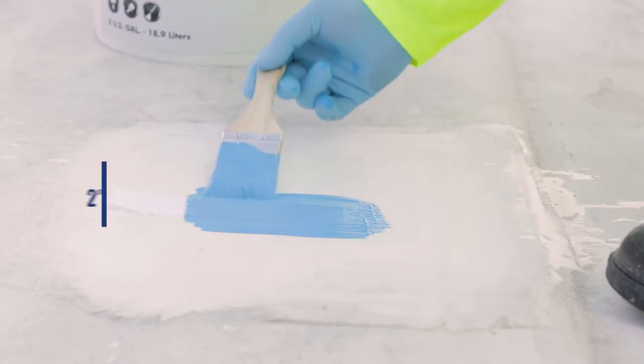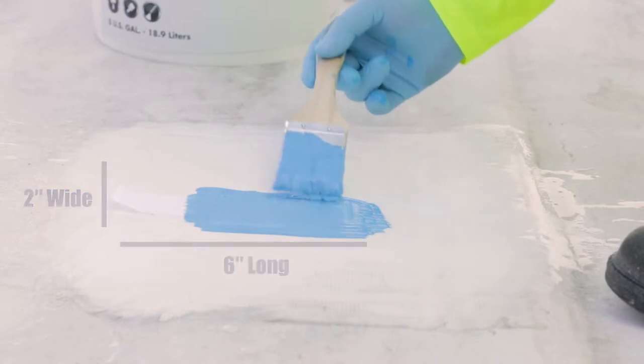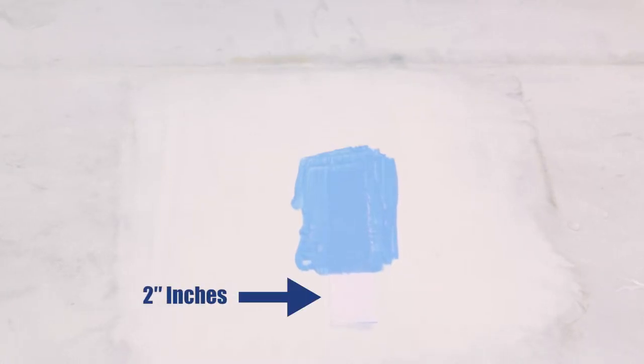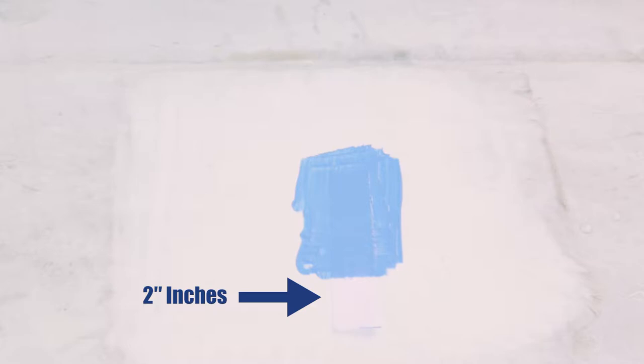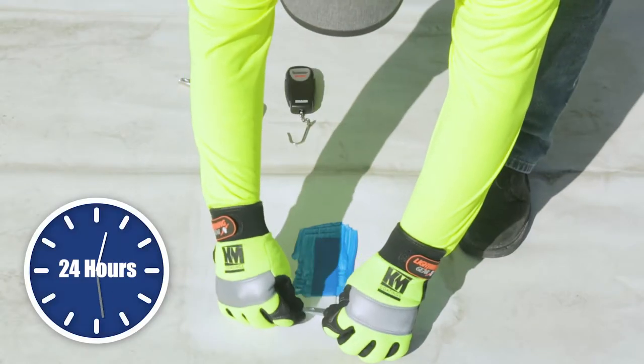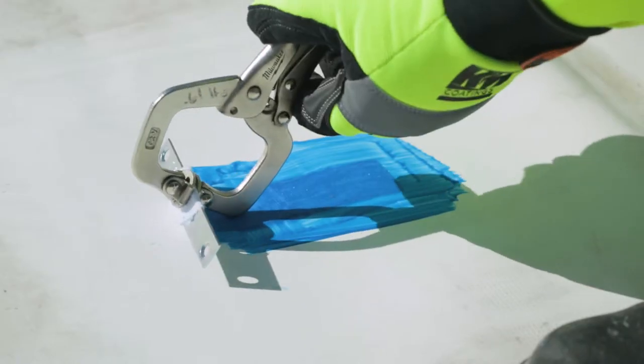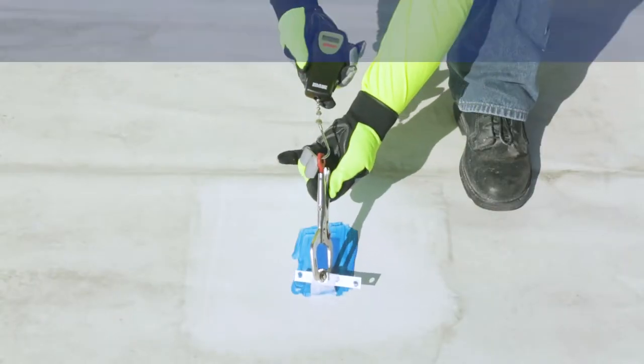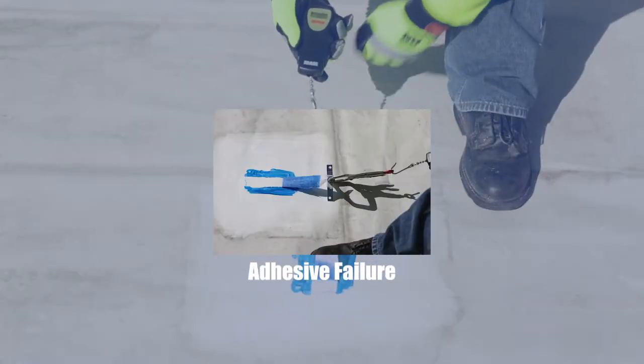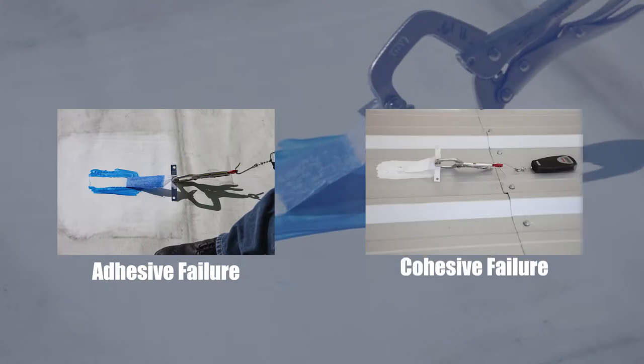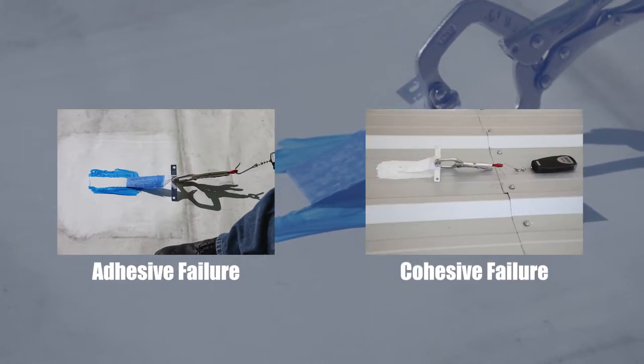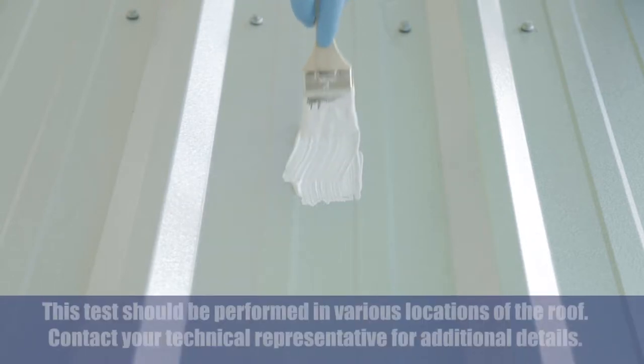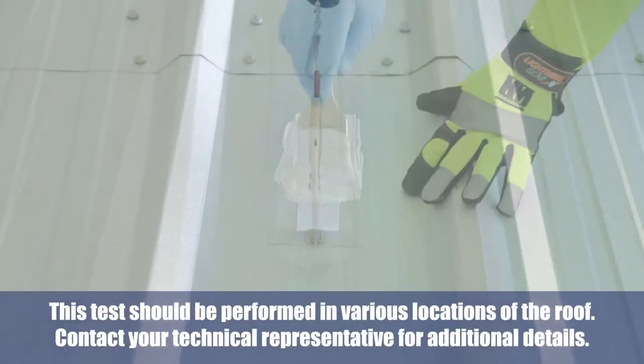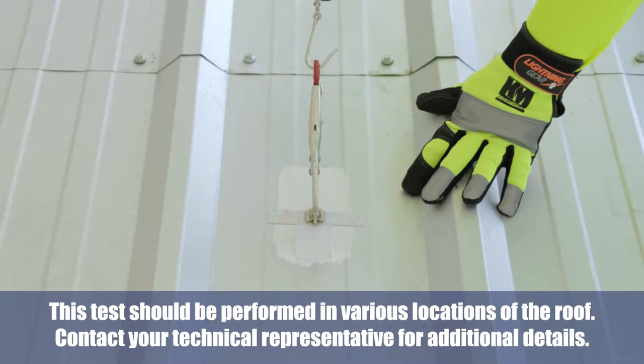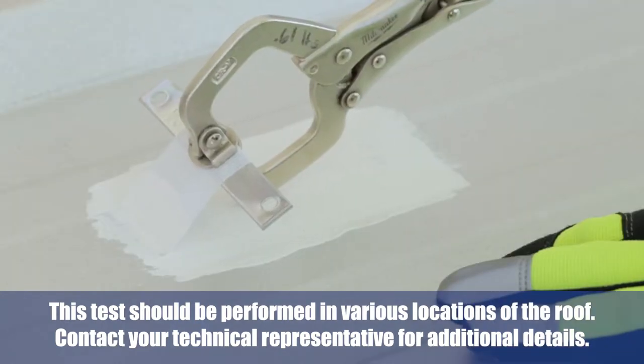The strip of mesh should be approximately 2 inches wide and 6 inches long. When applying the mesh, make sure to leave 2 inches uncoated to pull after product application and cure. We recommend a minimum dry time of 24 hours before the polyester strip is pulled. If the coating comes off the substrate clean, adhesive failure occurred and a primer may be required. If coating is left on the surface, it is possible the primer may not be required. The same test can be done with additional primers. For best results, a primer is recommended. Be sure to consult with KM Coatings Technical Services if you have questions regarding the field adhesion test results.